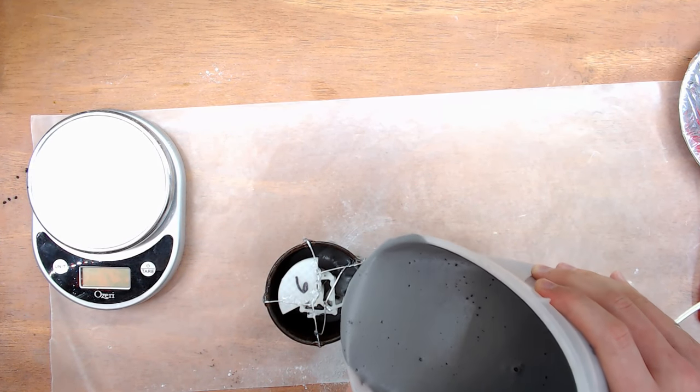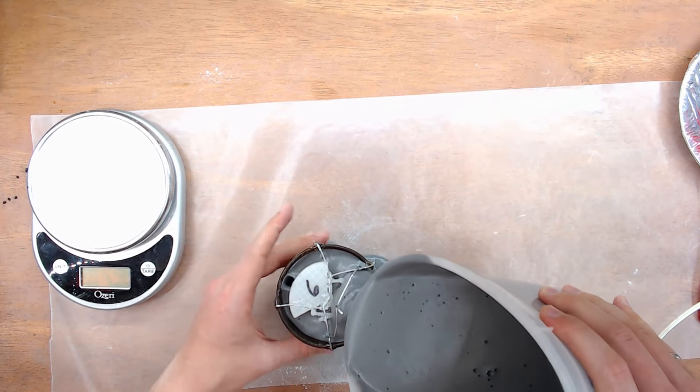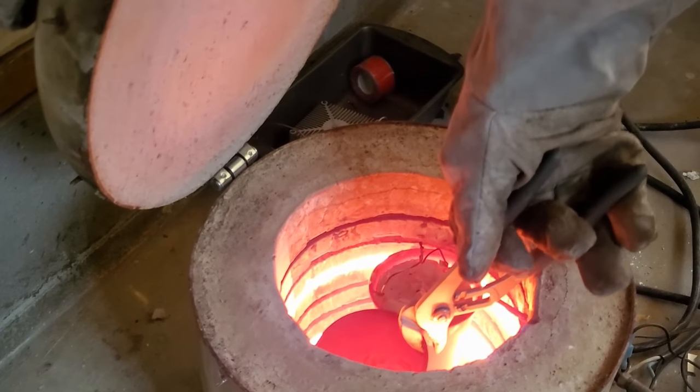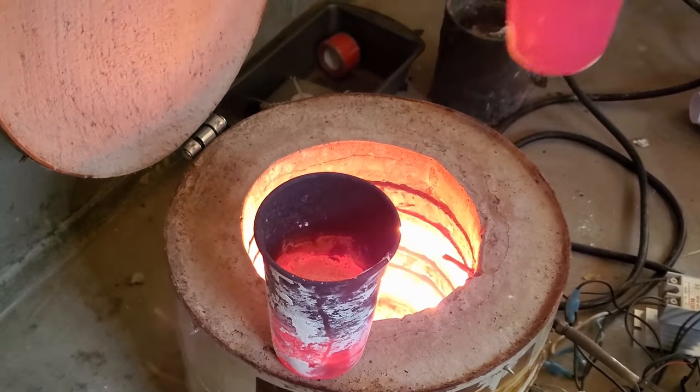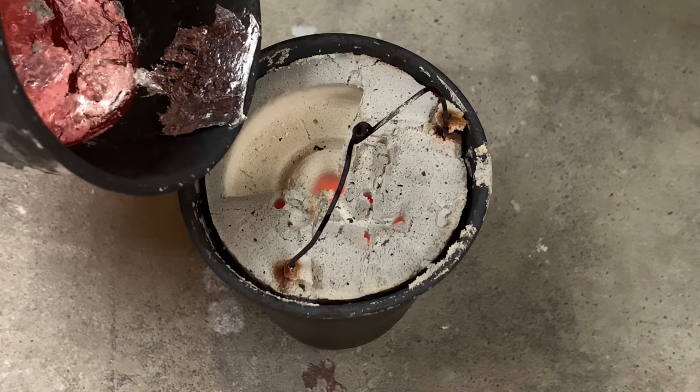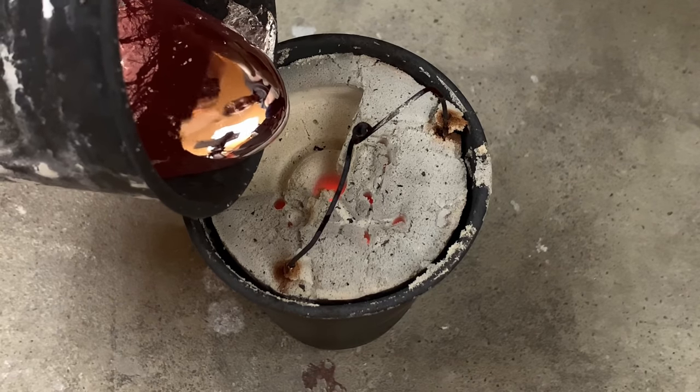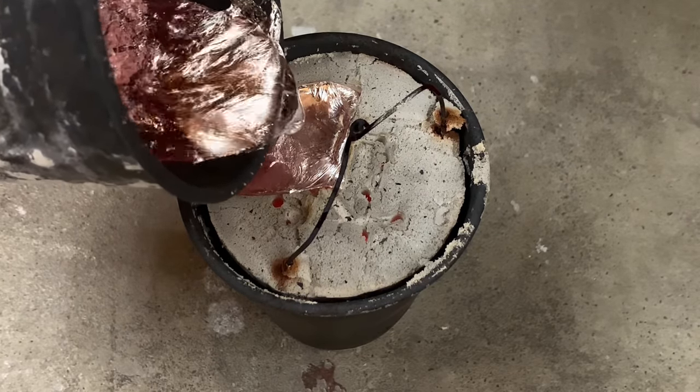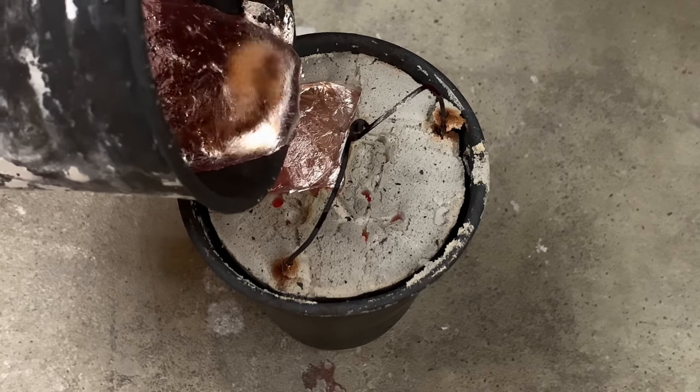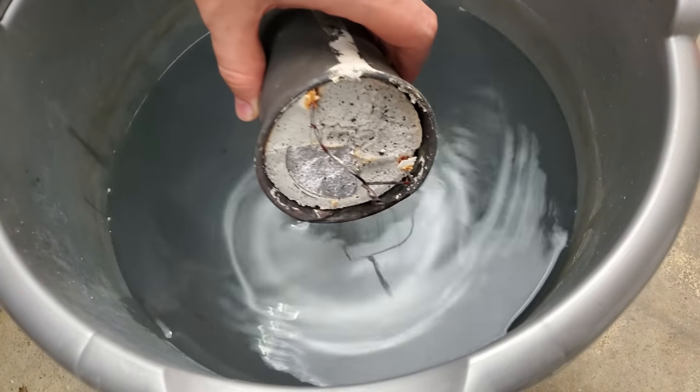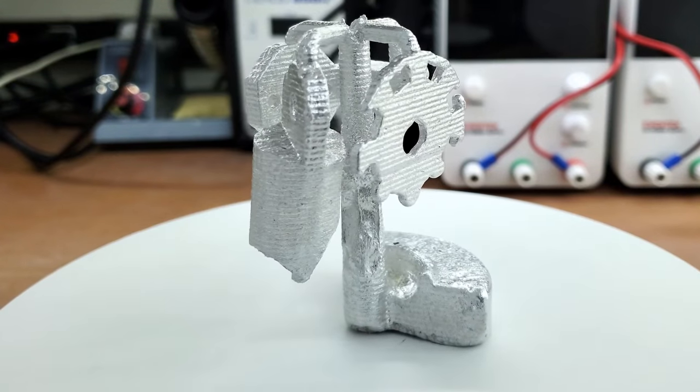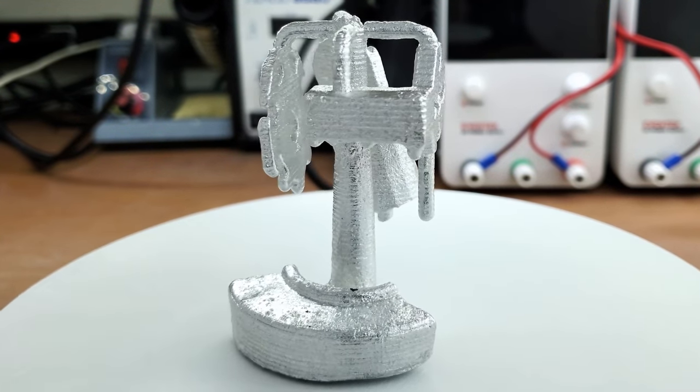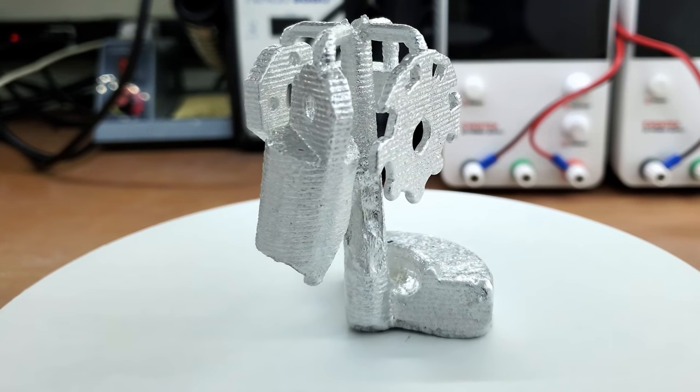So let's fix that. Previously I would allow the mold to cool for about five minutes before drenching. For this try I will allow the mold to cool much longer. One hour should do it. By the time I drenched the plaster the outer temperature of the flask was very close to room temperature. This tells me that the aluminum inside should be fully solidified. The drench doesn't make that satisfying sizzle anymore but two of these parts actually look somewhat usable. Most of the fine details are intact. There are a couple small imperfections but they would likely work. I can still do better.